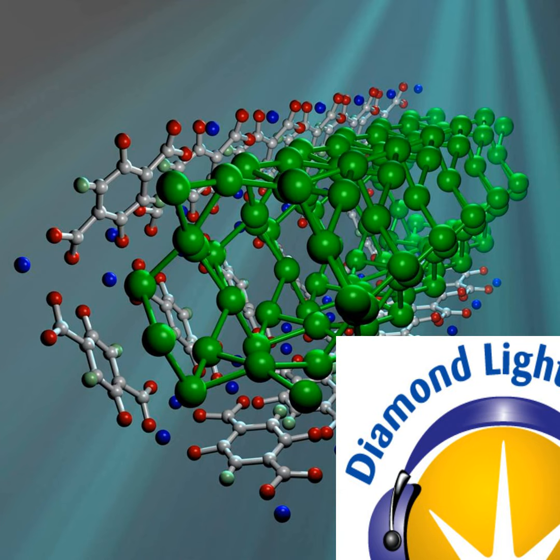And do you have an example, say, of a particular catalyst that you've been looking at in real time, in situ, and what kind of changes or effects you were seeing? One of the recent pieces of work we've looked at is a methanol oxidation catalyst. This is an iron molybdate system, and the phases present in that material are very important for the catalytic activity. The activation step for these materials has a calcination process at higher temperatures, and we're able to study this calcination at these different temperatures and work out exactly what conditions we need to make the active phase.